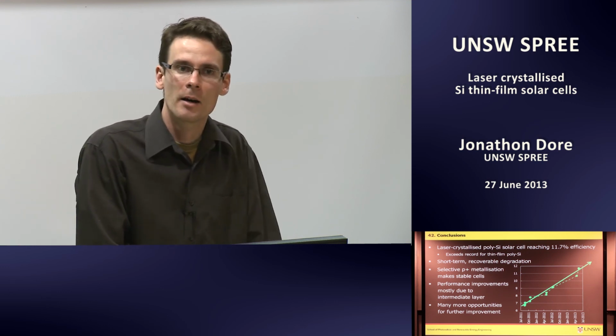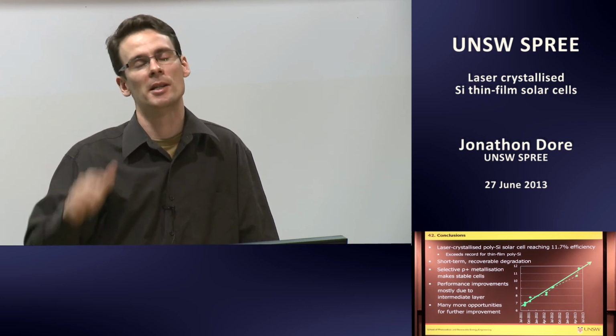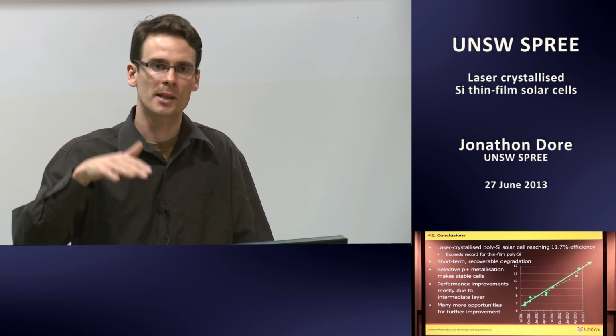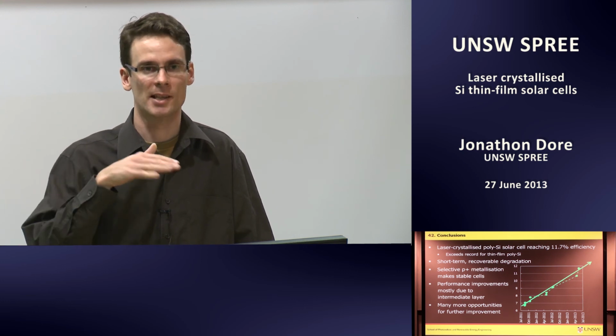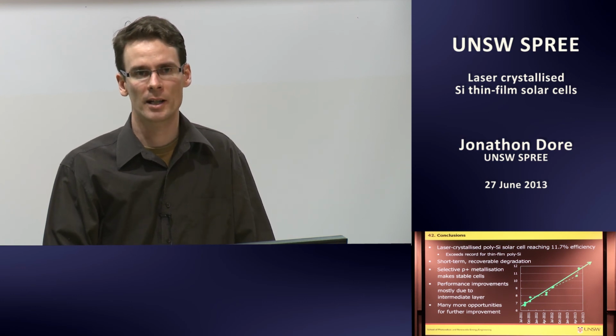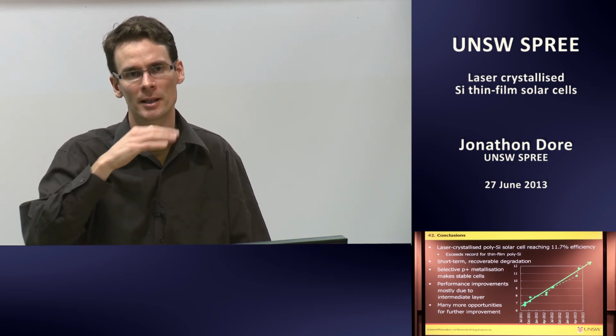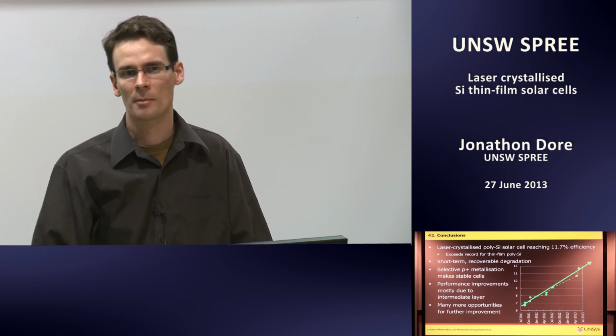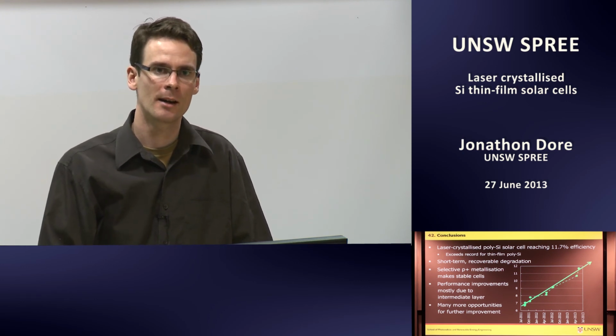I'd hope so, but one of the interesting things is that with a PECVD nitride, we had problems with the crystallisation. All these layers can mildly affect the wetting properties, even if they're the same material deposited by different means. When I used a PECVD nitride, I actually had quite a few almost microcracks occurring in the intermediate layer itself. So I wasn't able to get material that was good enough for a device test. I'm still looking at that, and hopefully we'll have time to complete that study before I finish my PhD.